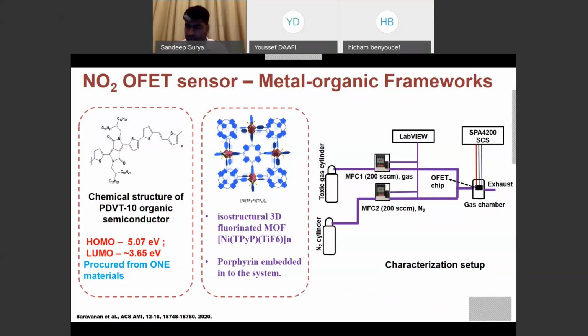Thus, we performed the analysis, and what we have realized is there is good enough selectivity of PDVT-10 organic semiconductor as compared to the other oxidizing and reducing gases, but the amount of gas detection and the amount of change in the output characteristics and in transfer characteristics of these devices were very small. Thus, we jumped into usage of another bilayer on top of PDVT-10 organic semiconductor. Here we have used metal organic frameworks.